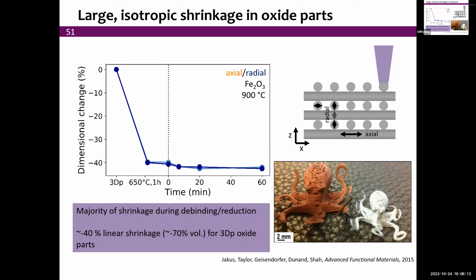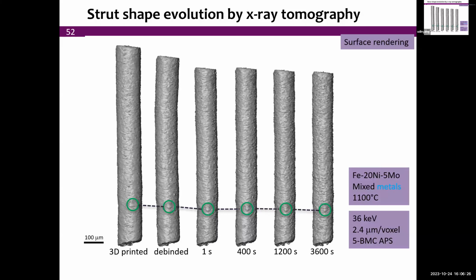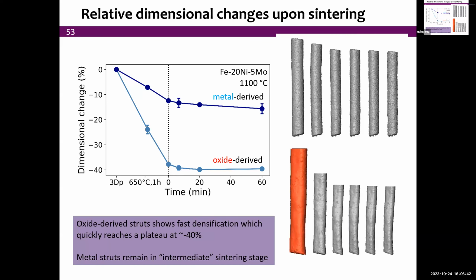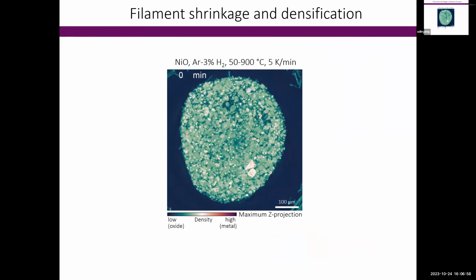And as shown here, as we go from oxide to metal, this is shiny. It's not white, it's really a reflection showing the metallic structure in the iron oxide. Meanwhile, we do the same evolution using mixed metal powders, which, if you remember, don't sinter very well. We only get a pretty incomplete sintering of the material because, again, the particles are much larger. And that's shown on the outside. If we now show the two together, we see the oxide-derived material shrinks right away and gets full density, whereas the metal-derived one ends up with this internal porosity and therefore much less shrinkage. So it stays in an intermediate or partially sintered situation.